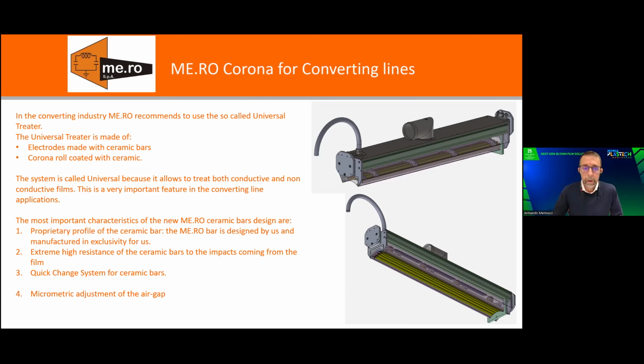Thank you. Okay. So we reverse the concept and we bring the dielectric on the ceramic bars, on the electrodes, as I told you. So we use the ceramic bars design. The most important characteristic of these ceramic bars is a special profile that belongs to Mero, and we are the only ones that can use it. Then we have given the system a strong resistance for the ceramic bars to the impact that is coming from the film, from the splice or from the film itself. Then we have a very, very important characteristic that I will show you later. It's a very easy system for changing the broken ceramic bars.